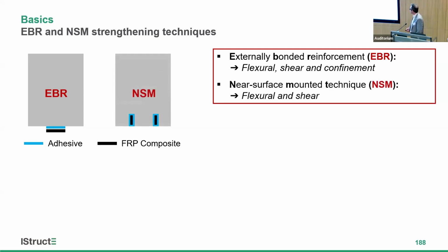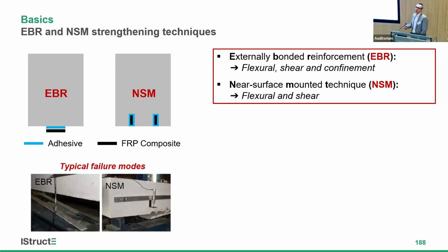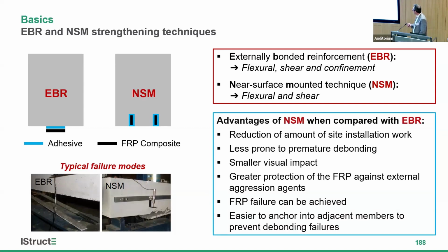The other technique is the near surface mounted. It is mostly used for flexural or shear strengthening. And you can see here in this case, what we have to do is to insert the composite material in the concrete cover of the element to be strengthened. Here are typical failure modes that we have already seen this morning, so I will not spend too much time with this, but in reality, when we compare this near surface mounted technique with EBR, you can see that this NSM presents more advantages like reduction of the amount of site installation work, less prone to premature debonding, less visual impact, as you can see here, higher protection of the system against external environments, and in many cases you can achieve the ultimate capacity of the material, in addition to the fact that it is possible to anchor at extremities.